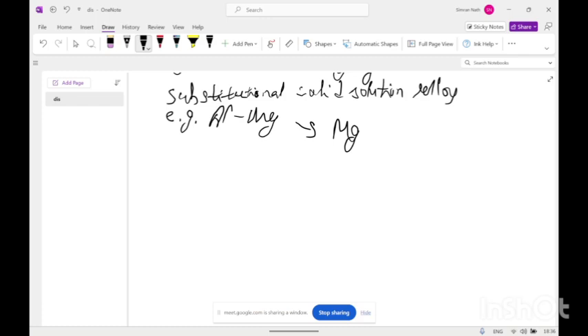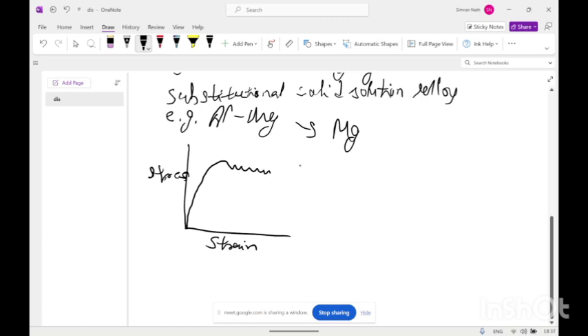that for strain aging we have to leave the material for a few months, but dynamic strain aging happens during the deformation only. Like this is stress and strain. So the variation in the yield point, if this type of curve is seen, this type of variation in the stress level with increasing deformation is called the serration.